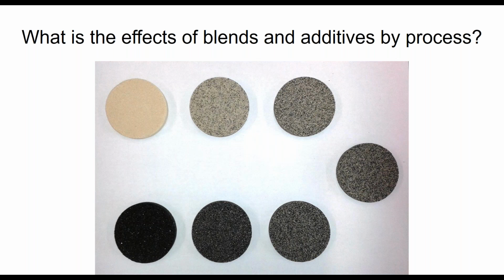So what we do to these new test specimens, we affect how they are blended or potentially the additives that we could place on them externally, like a refractory coating, or internally as other types of chemicals and compounds that we could add to the sand. Here on this slide, I'm showing you at the top left a silica sand system as a disc, and similarly on the bottom left, you're seeing a ceramic sand.